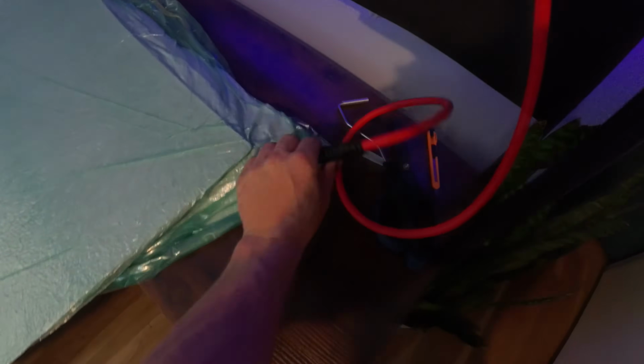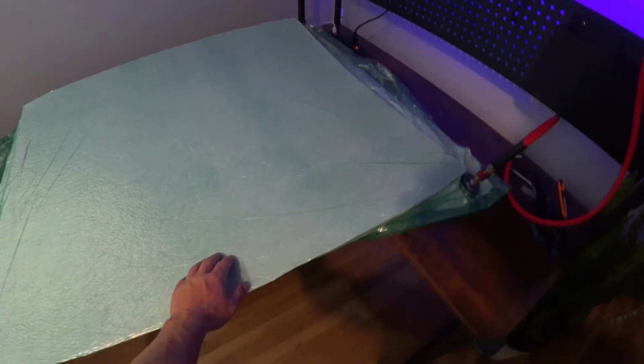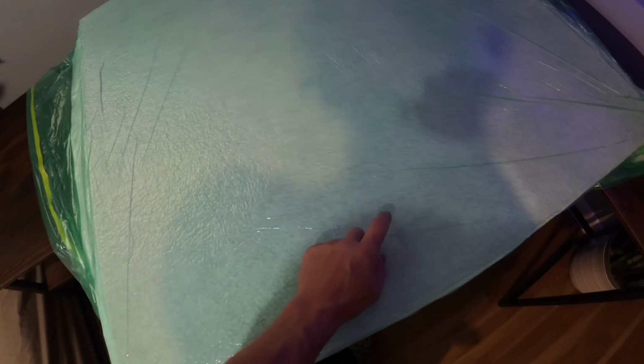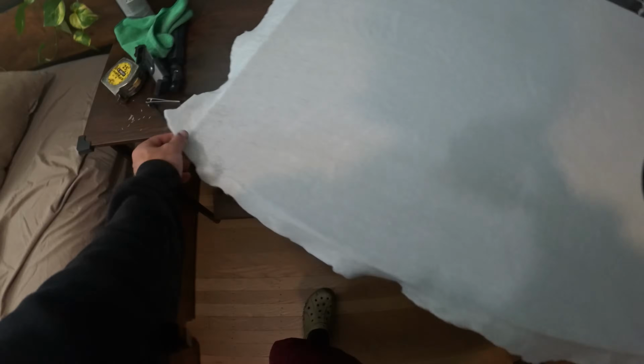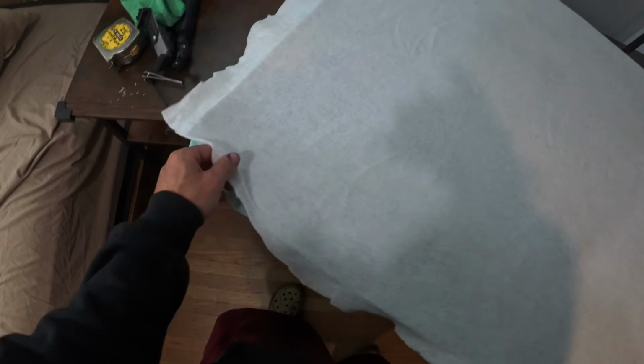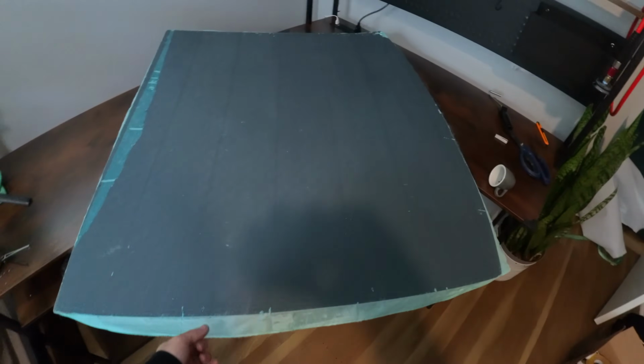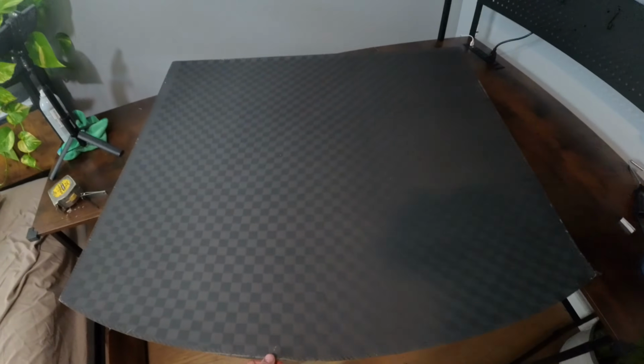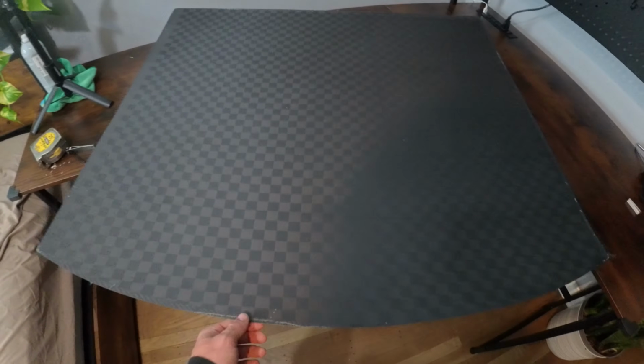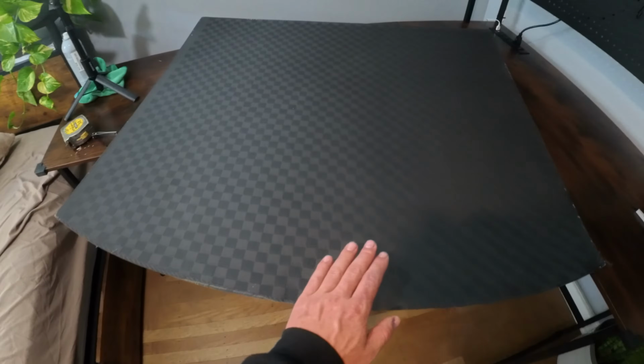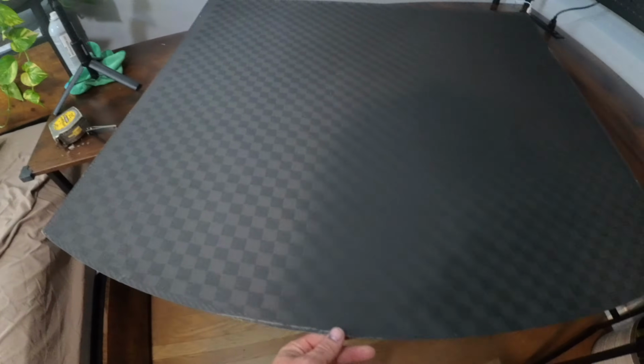You must ensure your vacuum bag is completely sealed or the setup will not hold vacuum. After ensuring the vacuum bag was completely sealed up with the gasket tape, I turned on the pump and quickly removed all the air out of the bag and held a tight seal. You will begin to see the peel ply material absorbing the excess resin if you did this correctly. After 24 hours to cure, pull the panel out of the bag and remove the peel ply and breather material from the panel. The peel ply gives you a nice uniform layer which has a gridded texture to it. This textured finish does not need to be sanded if you are adding another layer of carbon.